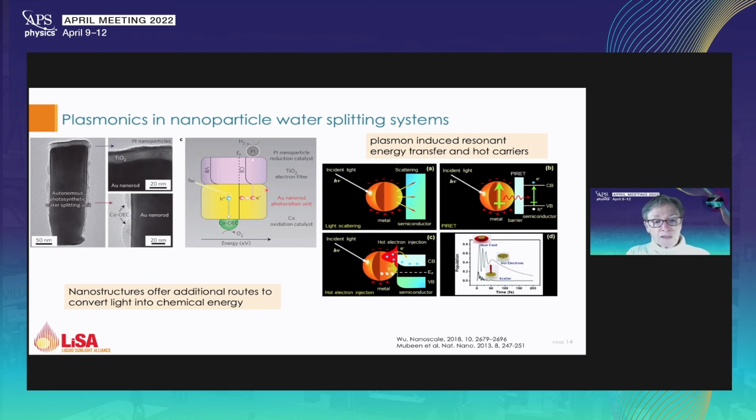Now, it turns out that in this arrangement, the gold nanoparticles actually undergo plasmon-induced resonant energy transfer. And this is very advantageous for being sure that even though the surface area is really tiny, you get maximum transmission of solar excitation, much better than you get through scatter.